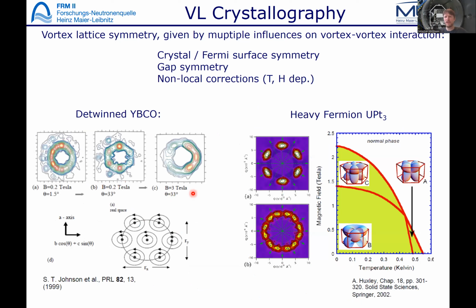There are, of course, more examples where this has been done. One very nice example is looking at YBCO, where also a deviation from the ideal 6-fold vortex lattice symmetry has been found. And YBCO is one material that Emma has been working on. Then, of course, looking at the gap symmetry, looking into unconventional superconductivity, a very nice example is the work that has been done on the uranium platinum 3 compound, where depending on where you are in the superconducting phase, a different symmetry of the vortex lattice has been found that, of course, reflects the symmetry of the superconducting gap.